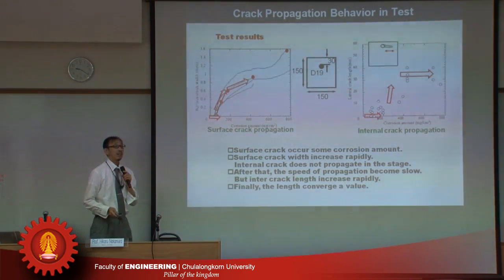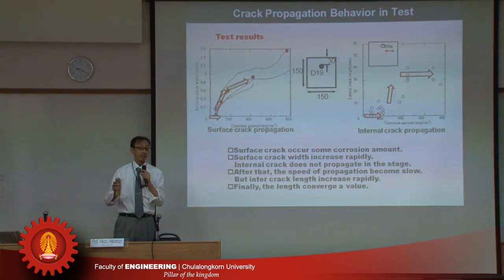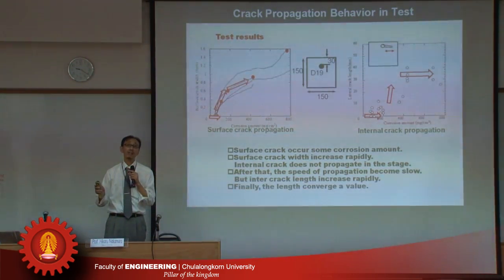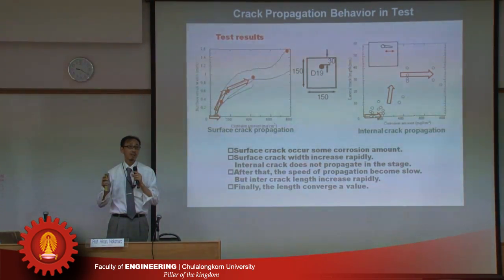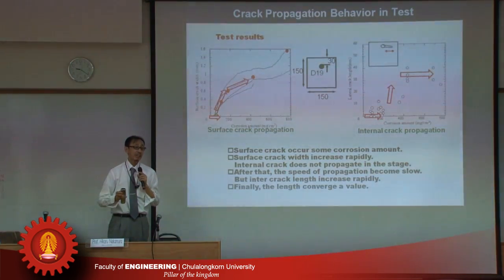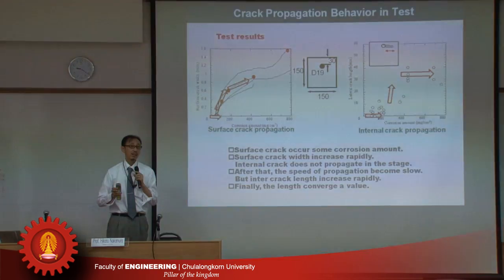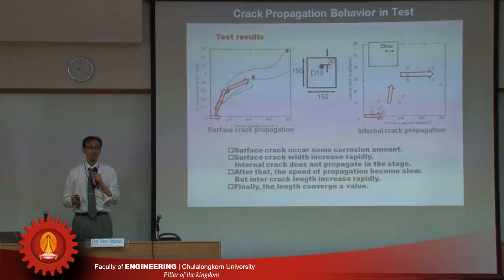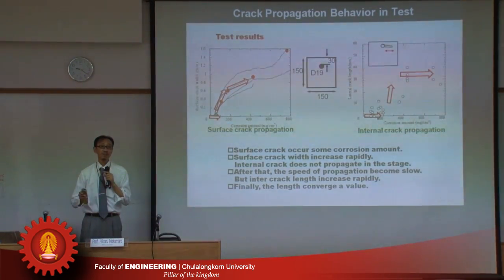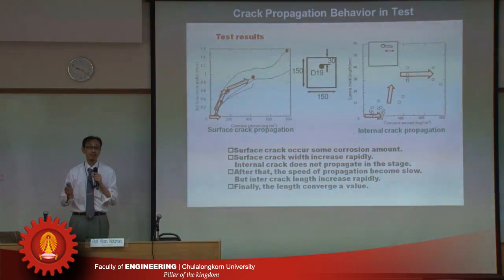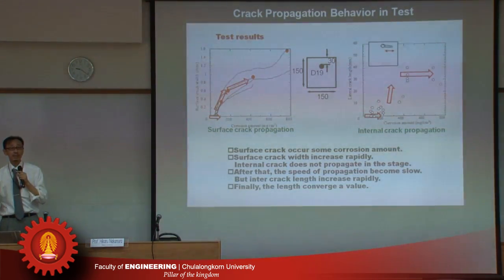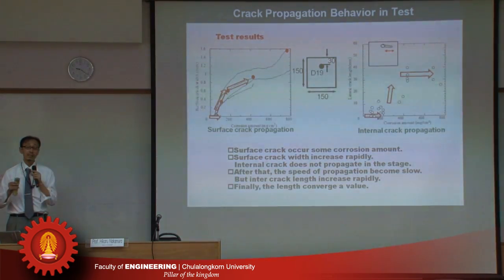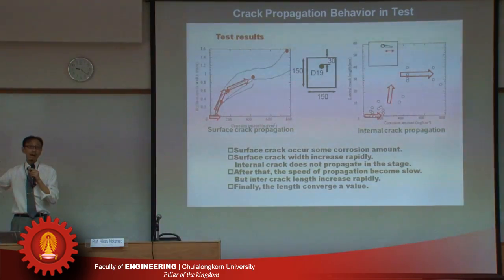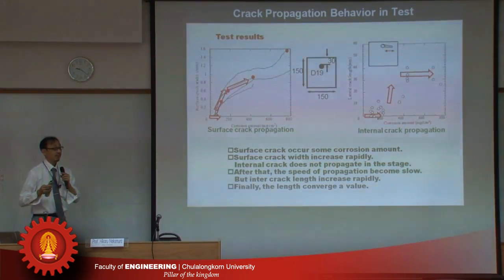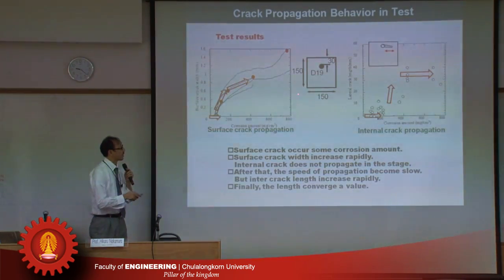So the propagation of the surface crack width and of the internal crack is quite different. If there were a strong relation, it would be easy to predict the damage of the concrete structure. But from this result, we can understand that we cannot predict the damage of the concrete structure only from the observable information of the surface crack. That point is very important. However, this is just one example, and the relationship between the internal and surface cracks is some function of the cover thickness, the spacing of the rebar, etc. So we have to consider these parameters that affect this behavior.